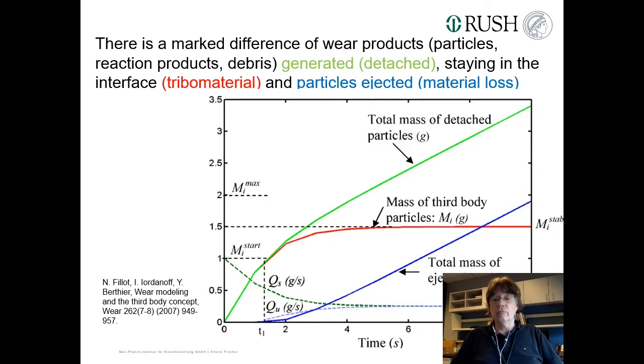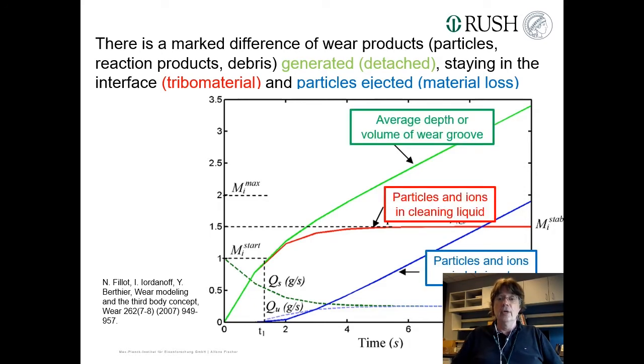And with respect to tribological measurements or real application, you can transform that into the average depth or volume of a wear groove, which does not represent the wear loss. Not per se, it could, but it must not. The wear loss is the particles and ions and mass you find outside of the system, maybe in the lubricant, which can be analyzed. The particles can be analyzed as well as the ions. And if you clean your surfaces afterwards and you don't spoil that cleaning liquid down the drain, so in the gutter, then your evidence is gone for sure. So you can analyze that as well.